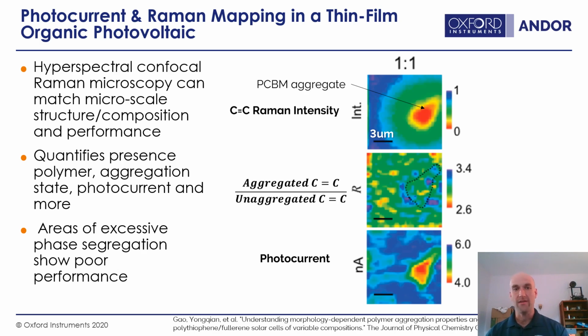So it turns out that if you look at, and this is a tiny patch, this is a 3 micron scale bar, a tiny patch of a functional device, you can see that there's quite a bit of contrast in the carbon-carbon double bond stretch Raman intensity. So this is a PCBM aggregate in here. I believe I showed you a few slides ago, you have these little spots that grow with thermal annealing. Some thermal annealing is required to get the device performance maximally efficient, but too much, and you get this over phase segregation here. But not only can you see a lack of polymer in this PCBM aggregate, I guess it's displaced the polymer around it or grown over the polymer around it as the PCBM has coalesced and aggregated.